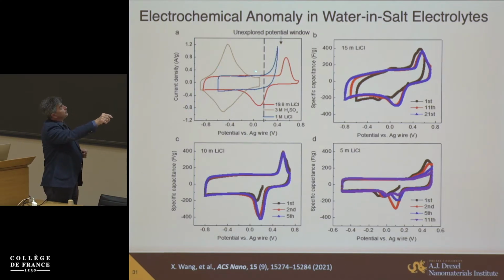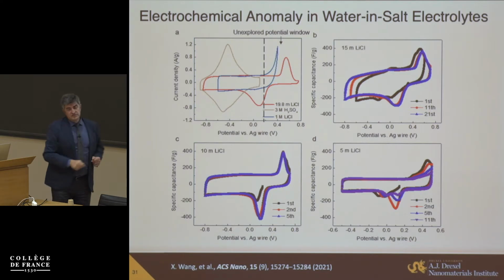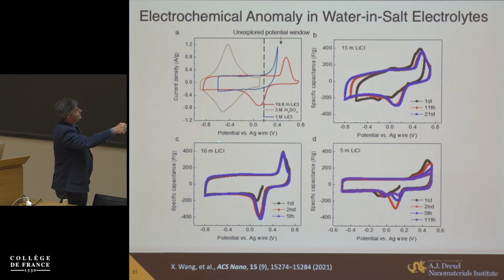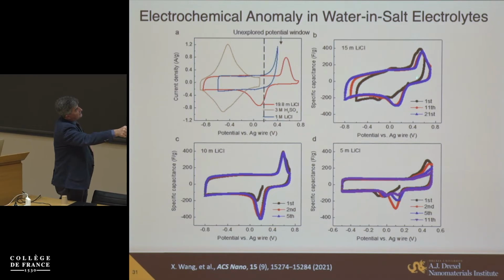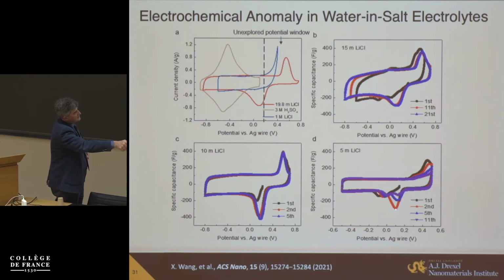This is the CV curve I showed you with protons, with double layer and this redox peak, oxygen to OH. This is sulfuric acid I showed you just before. If you have low concentration lithium chloride electrolyte, you will get just the double layer behavior. If you try to push towards positive anodic potentials, there is oxidation of MXene by water. But if you take 19.8 molar lithium chloride solution, the maximum concentration reached in water-in-salt electrolyte, we can push much further. You see, we're coming close to 0.8 volt, and there is still basically no water splitting. But we have a couple of those peaks. And you can get it with 15 molar, even 10 molar concentration; in the first cycle it's weaker, and after a couple of cycles it develops and remains stable. But if you go to lower concentration, 5 molar, it appears and then starts disappearing, degrades.